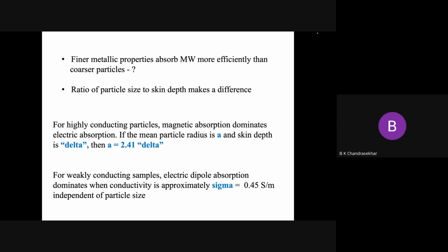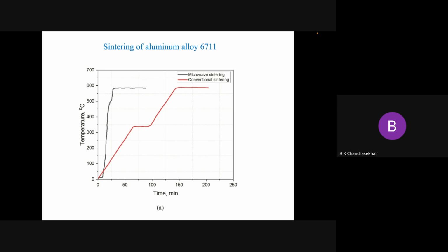Whereas for weakly conducting samples, I am talking about weakly electrically conducting samples, the electric dipole absorption dominates when the conductivity is approximately about 0.45 Siemens per meter, independent of the particle size. That means you don't have to be bothered about the particle size when you are dealing with weakly electrically conducting samples, whereas for conducting particles, you have to be worried about the particle size. And people have found that, for example, for aluminum alloys, even a coarser grain of aluminum, one can sinter using microwave very easily and very efficiently with a very short duration of less than 100 minutes, whereas the conventional heating takes more than 3-4 hours. And this is taken from the literature. The black curve is for the microwave sintering, and the red one is for the conventional sintering.